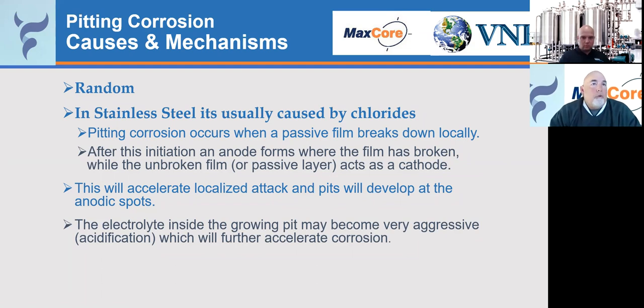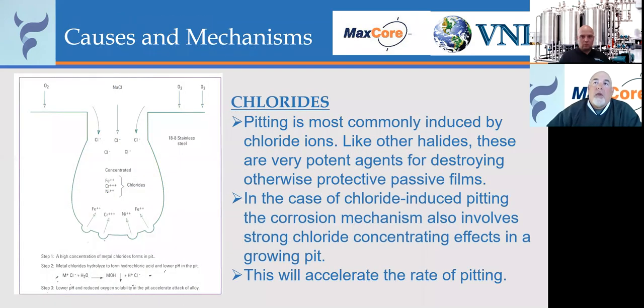This will accelerate the localized attack and the pits will develop at those anodic spots. And the electrolyte inside that pit may become very, very aggressive. As you start to fill that pit with liquid, you limit the amount of air and contact that happens there, and that can become more concentrated. And when that does, it becomes much more of an accelerant as well. So what can happen during that particular process is you may have a very, very small pit up on top of the surface of the steel, but as this starts to corrode down into this steel, it starts to open up in a teardrop type shape.